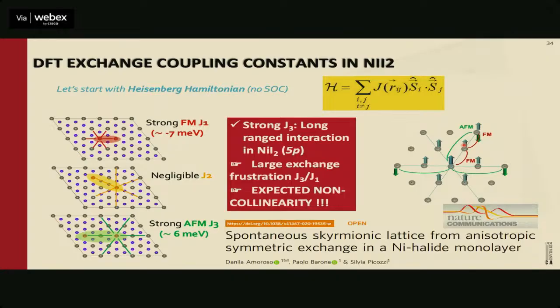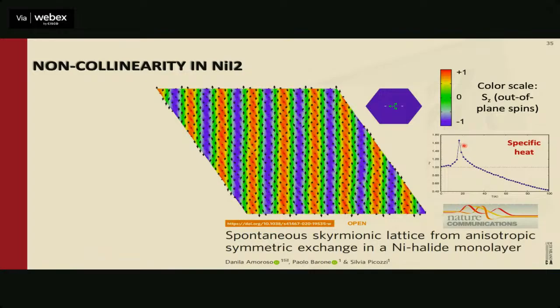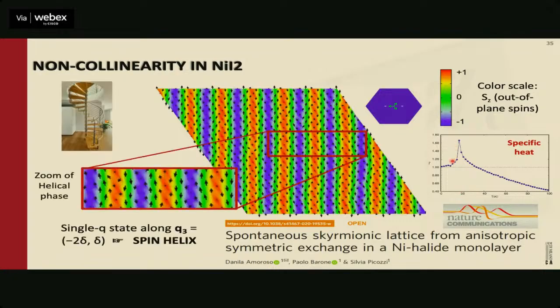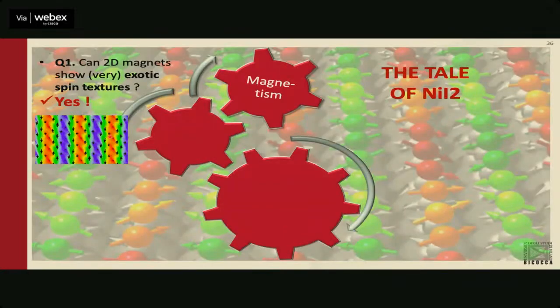The fact that from the exchange constants you can predict some non-collinearity is part of the strength, let's say, of DFT. Even more, by mapping your total energy into a spin Heisenberg Hamiltonian and doing Monte Carlo simulation, you can infer that the Curie temperature is of the order of 30 Kelvin or so, and you can see that there's a spiral. In particular, it's a peculiar spiral called a spin helix. It's like a helix, like a staircase in your home. From site to site, the spin rotates like in a staircase. And so I have the ingredients in nickel I2 to have complex magnetism.